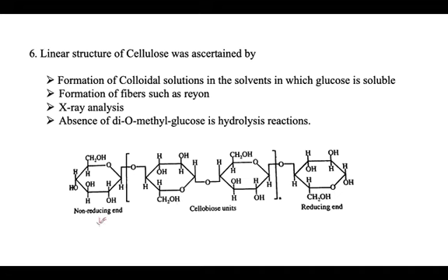That non-reducing end is where we are getting the four substituted methyl, tetramethyl. We are getting the hydroxy group here, and here, and here. So that is why we are getting 2,3,4,6-tetra-O-methyl-D-glucose. That was around 0.6% on hydrolysis.